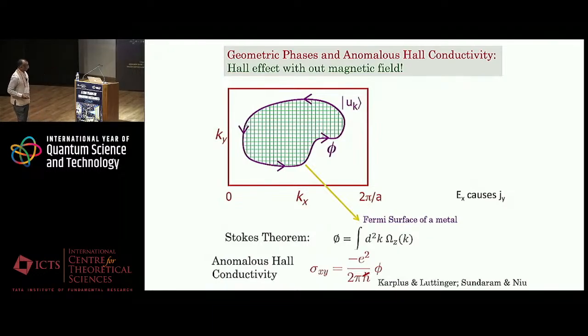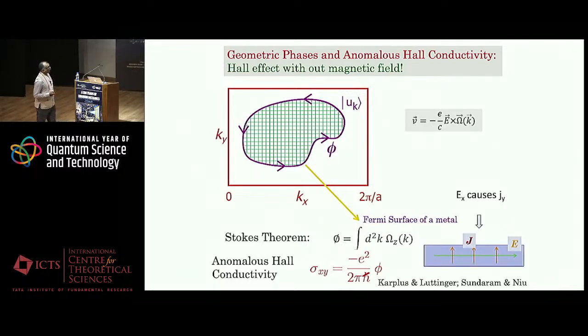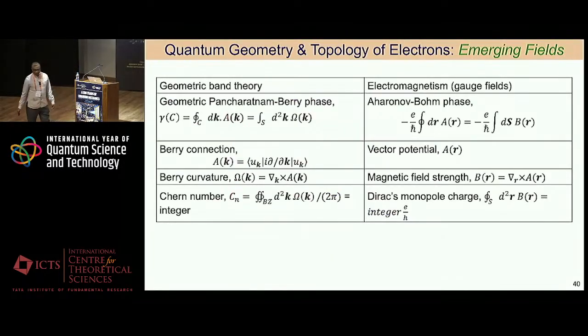Then it has been shown long ago that if you have a two-dimensional metal and you calculate the Berry phase like this along a Fermi loop, a closed loop, you get basically phi, and the off-diagonal conductivity, or Hall conductivity, is essentially this quantum times phi. And that means if you apply an electric field along the x direction, it will create a current along the y direction, and that's the anomalous Hall effect.